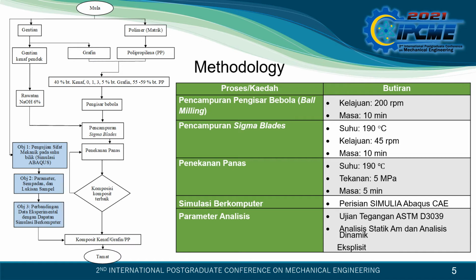The reason why we combine it with graphene is the idea to improve the mechanical strength, for example the tensile strength performance, because the addition of graphene can increase it, but only up to several percentage. If we put so much graphene in it, it will somehow deteriorate and cause the tensile strength to drop. That is what we try to alter and study.